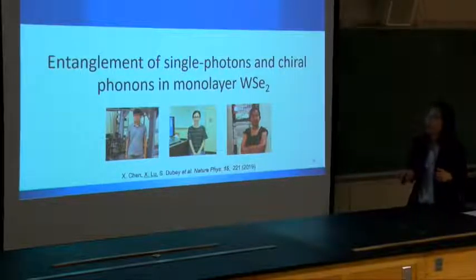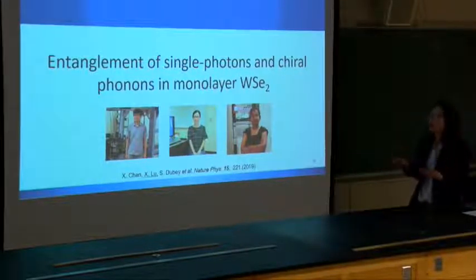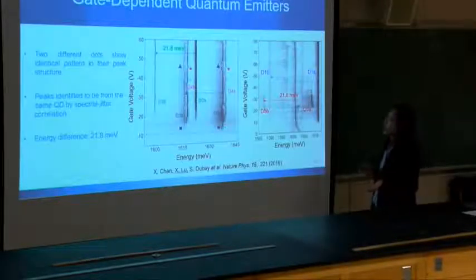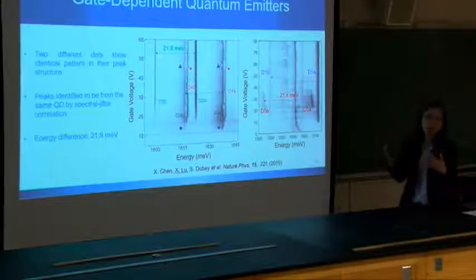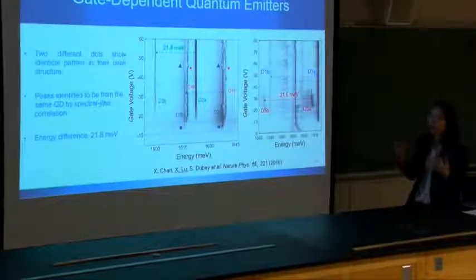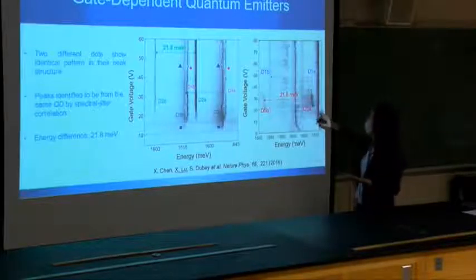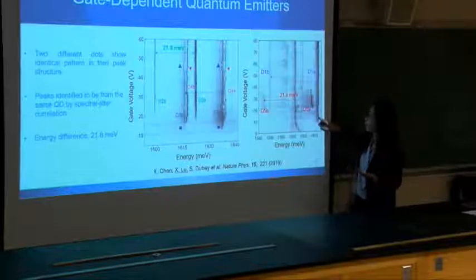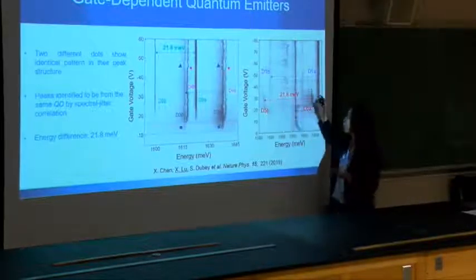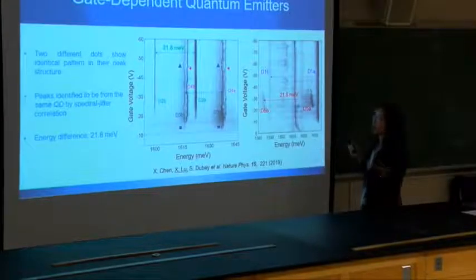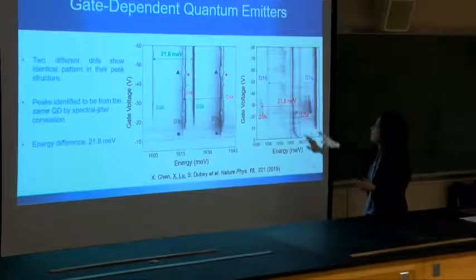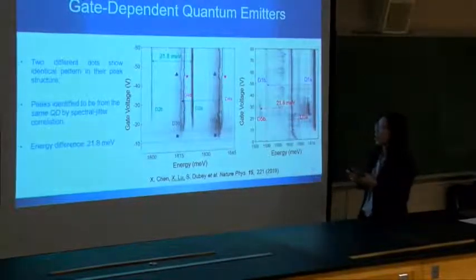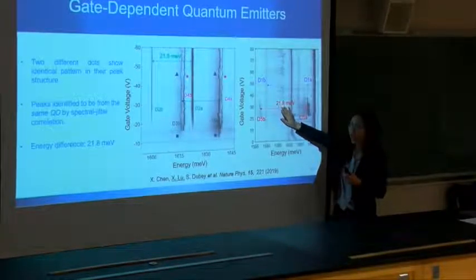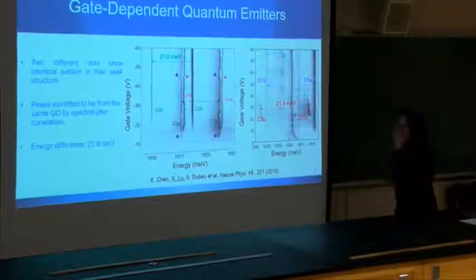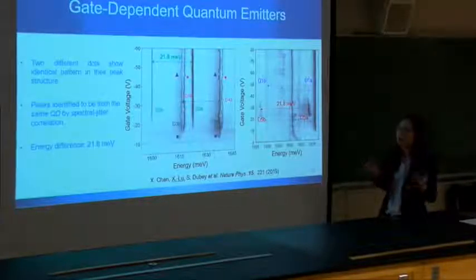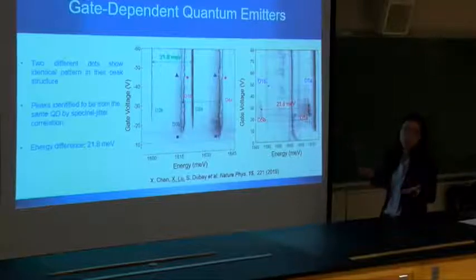Okay, and then it comes to the third part. It's about entanglement of single photons and chiral phonons. So here in two samples, we observe a quantum dot group, or quantum emitter group, and below one neutral quantum emitter, exactly 21.8 milli-electron volt below that, we see another doublet group, whose spectrum wanders with the same pattern, and they show up at the same voltage. And it is always precisely 21.8 among eight groups. So the first thing coming to our mind is, could it be a phonon replica? Because the energy is too precise.